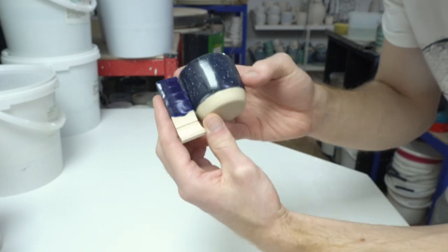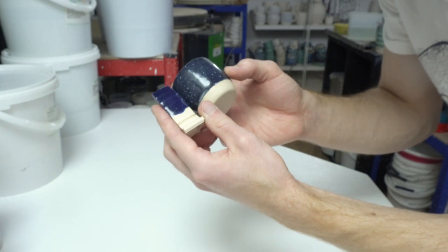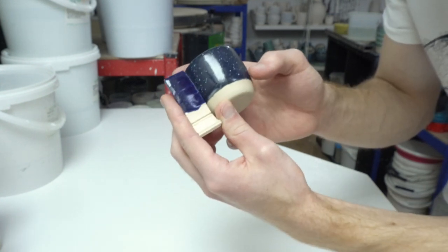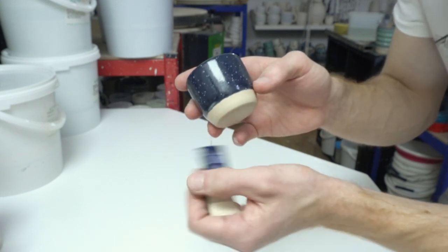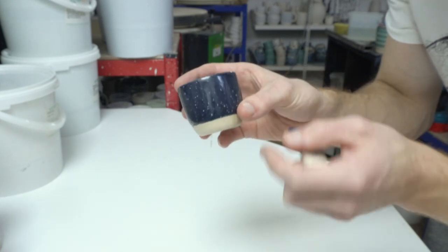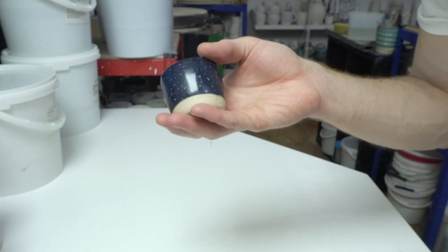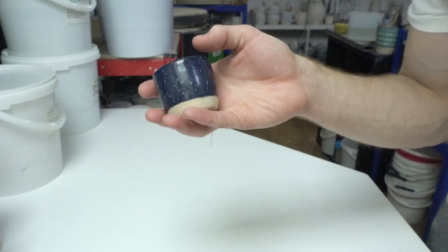So I'm going to revise the base again slightly, probably decrease alumina just a bit, and maybe a bit more boron, if you don't want to make it too runny, or the speckles won't keep their position. The reason that it's quite a stiff base is intentional, so that they don't flow, because otherwise what you end up with is smears instead of spots.